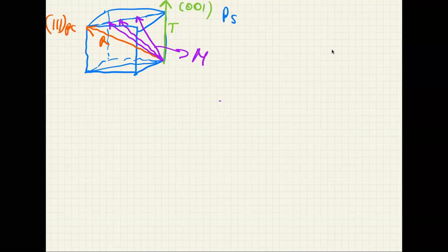And that means that with external electric fields or elastic fields, we will very easily go from here to here or anywhere in between. So that monoclinic phase comes naturally, at least intuitively you see it. If this and this have the same energy, then anything in between them should have approximately the same probability of appearing. So that this monoclinic phase appears between rhombohedral and tetragonal phases is not that unusual.